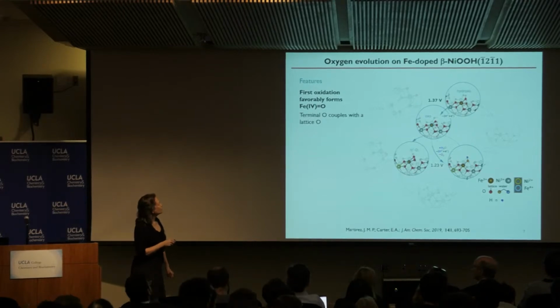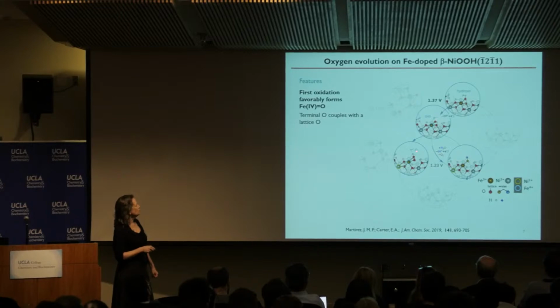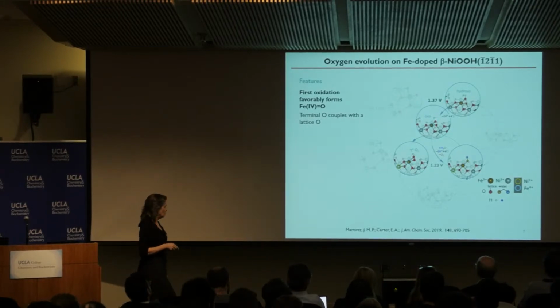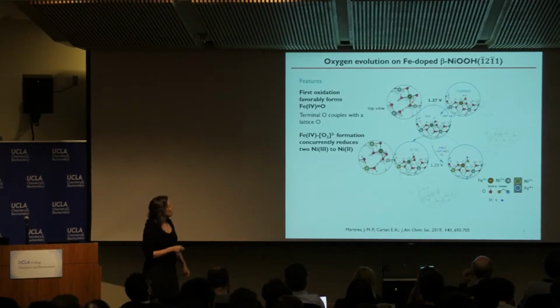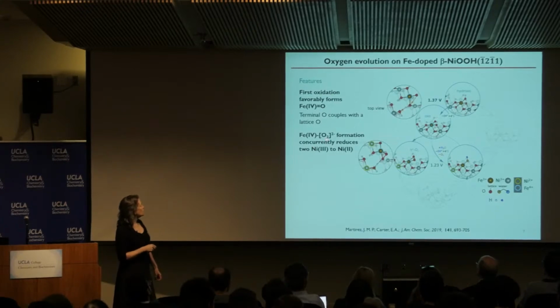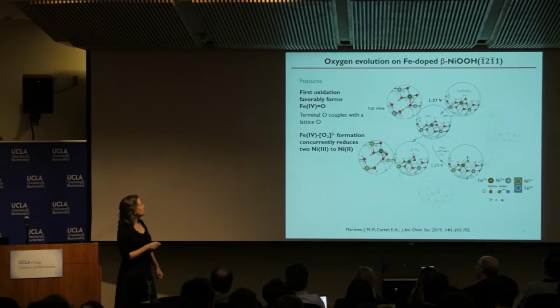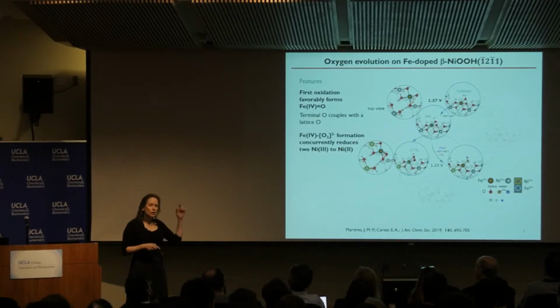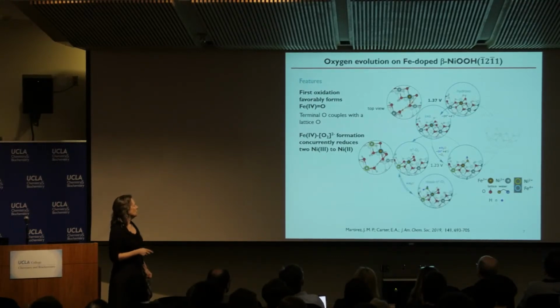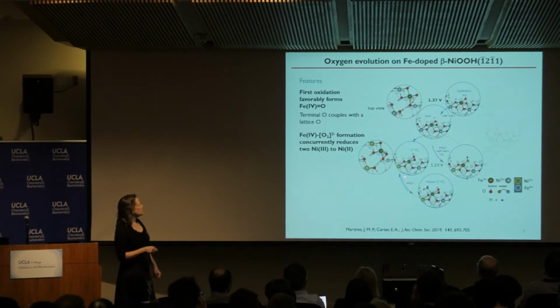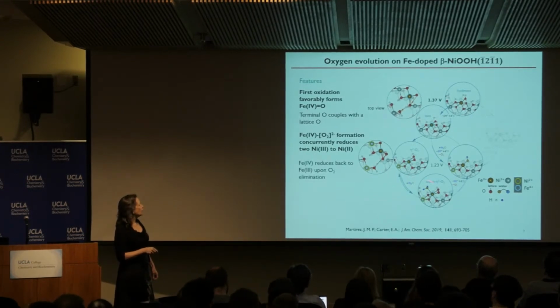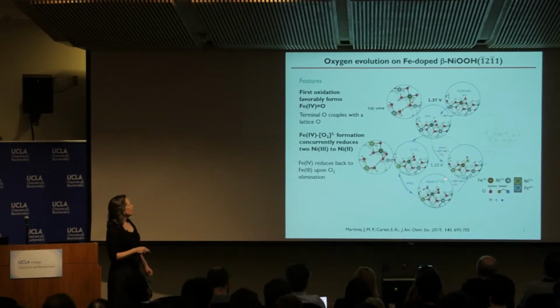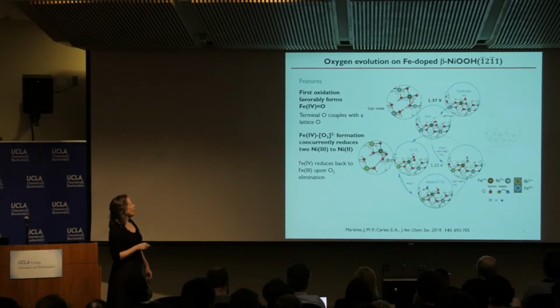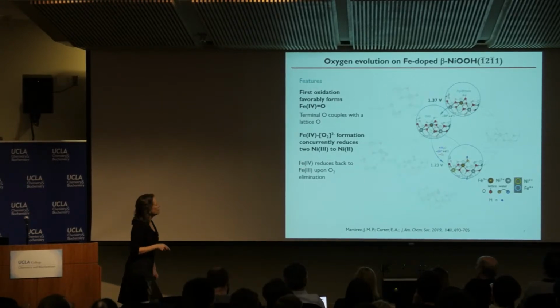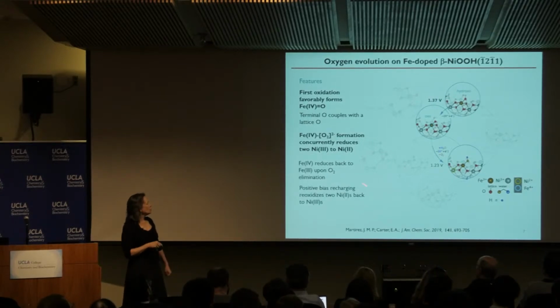Breaking that down, what happens actually is that this iron oxo attacks a lattice oxygen to form this η2 O2 species. And then, in fact, what happens is that the formation of this dioxo species reduces two of the nickel(III)s that are in this material to nickel(II). And that turns out to be very important. We're going to understand why that helps facilitate the reaction in a little while. Then water gets adsorbed, and then the water essentially deprotonates, and the system becomes more oxidized. And the electrons from the release of O2 actually then have the iron(IV) getting reduced back to iron(III). And that's the kind of catalytic cycle that takes place.